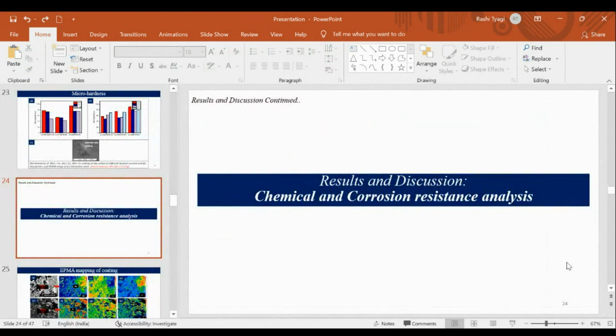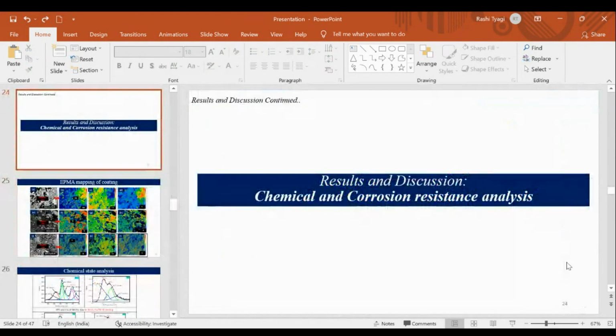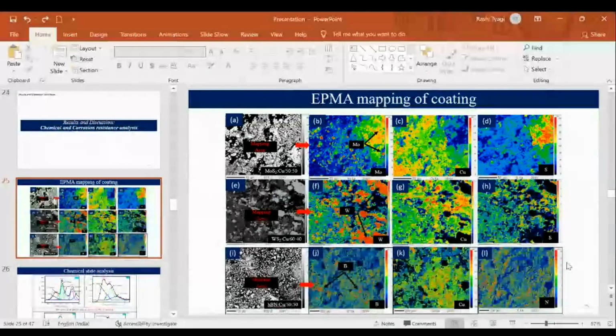Now the chemical and corrosion resistance analysis in this work. Chemical analysis means we have performed EPMA analysis, electron probe microanalyzer analysis. The electron probe is used similar to the EDS process, but it gives you a spectral distribution of the elements in the coating. It gives you colorful images showing how the elements are depositing, whether they are uniformly deposited or not. So EPMA is performed to check the uniformity of the coating.